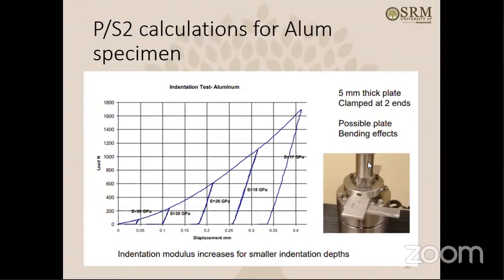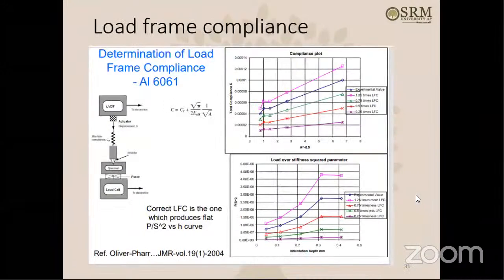Also the bending effect, like if you have a thin specimen like this, and you are applying the indentation, it may bend. So all those things are also there. To come up with a methodology for removing this load frame compliance, as you can see, the load frame has a certain kind of stiffness characteristics, and this is the equation here which uses the load frame compliance. C is the total compliance, and Cf is the load frame compliance. Okay, and if you plot total compliance versus this A value here, and that P over S square parameter is used for getting the correct value. So if you plot P over S square against indentation depth, the correct load frame compliance is the one which produces a flat curve of P over S square. Okay, look at this bottom curve here, and that is almost flat.